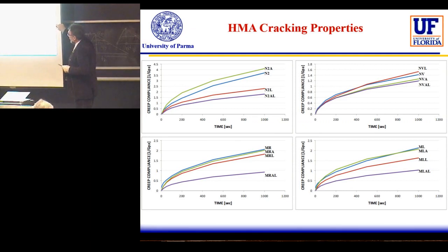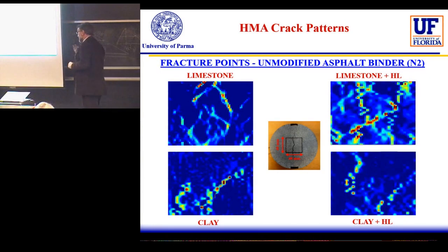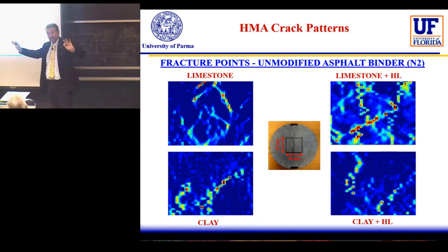Even looking at the creep compliance of the different mixtures as a function of the different combinations of filler and binder, we again have a different mechanical response. The most evident change is in the crack pattern in the different materials. We can clearly see here in the IDT, so in the mixture, that when we have limestone and clay, different crack patterns appear. I show one, but believe me, we found similar behavior and similar differences in all the mixtures.